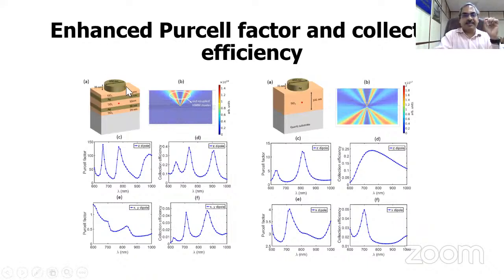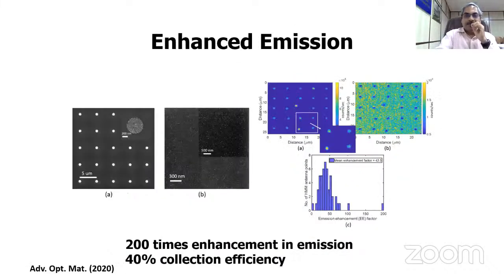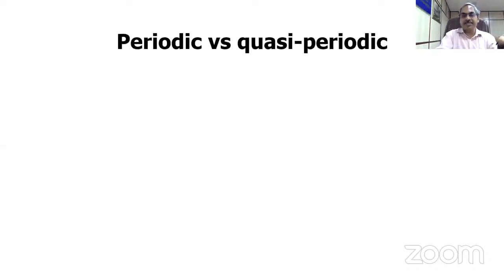We showed this by having a patch antenna on the top, and a single quantum dot put inside this central layer. So you get very directional emission, because when you're talking about single photons, the room light has of the order of 10 power 15 photons coming, right? We are talking about collecting a single photon which is emitted by this nanoparticle and then bringing it out and detecting it, okay? By having this hyperbolic metamaterial, we are modifying the so-called density of states. We are making it possible for this photon to come out of the nanoparticle and into this hyperbolic metamaterial medium, and then this antenna on the top is going to help us in directing it in one particular direction, right? So we demonstrated such things, and also single photon emission from these structures, right?